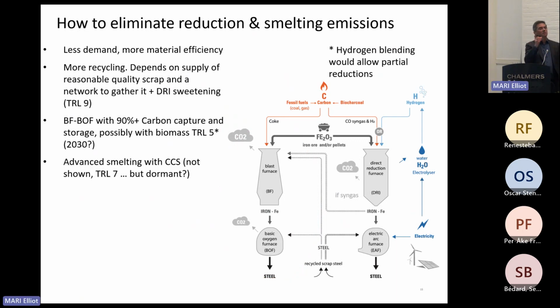Another technology that was the preferred option for decarbonizing steel before we thought in between BF-BOFs with CCS and HDRI. And the idea is you kind of eliminate a few steps. You just put coal in, you inject oxygen into the reactor. There was a lot of work done in Belgium, I believe, as part of the ULCOS project. Eventually, Tata walked away with the IP. It showed that it's quite possible to make steel that's more efficient, that uses less energy, but it also produces a concentrated flow of CO2 coming out of it, right? Which makes it a lot cheaper and easier to do CCS. But again, Tata is sitting on HIsarna right now, and we don't know what's going on with that project unless somebody else in the room knows more than I do.